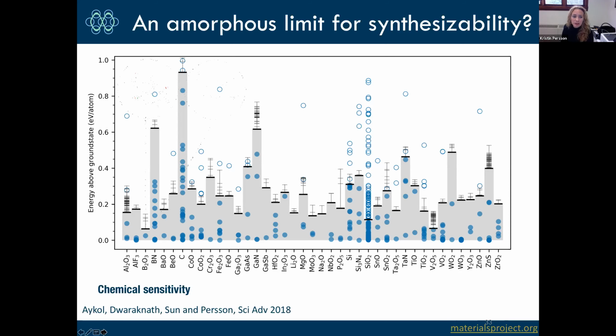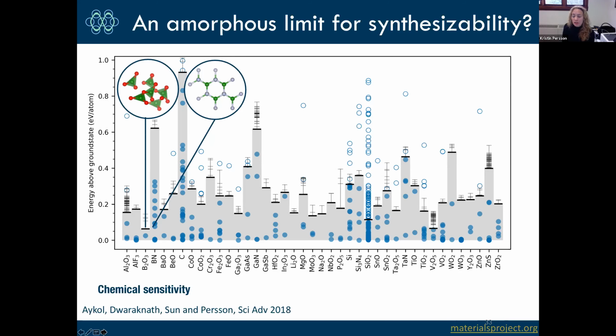So let's take a few examples. If you look at boron oxide and boron nitride, boron oxide doesn't actually mind being amorphous as long as you're keeping the local little boron oxide tetrahedra. They can float around in different environments. So the amorphous limit for boron oxide is pretty low. It's only about 50 meV per atom. But boron nitride hates being amorphous. So that's where you have a much larger window of synthesizability of other polymorphs, because the amorphous limit is not so competitive. It's up at 600 meV per atom, which is starting to tell you a little bit about why nitrides have such a high degree of metastability, because basically they hate being amorphous. So it's not a competitive state.